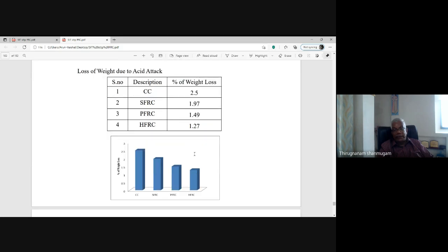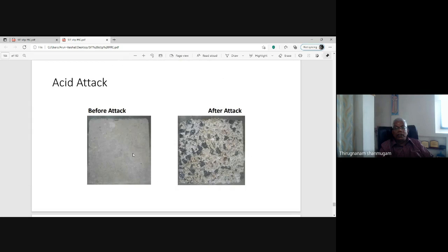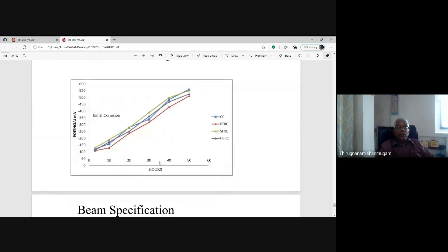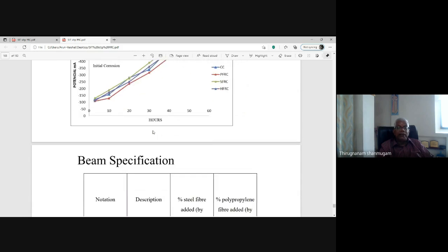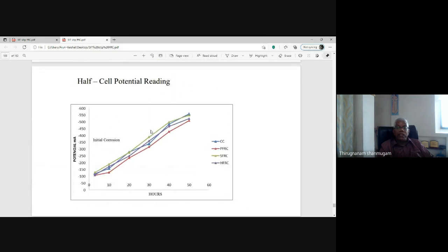Loss of weight is a durability criterion. Loss of weight in acid attack, sulfuric attack, is very much less, nearly 50% less. So hybrid fiber reinforced concrete is much more resistant to the acid attack. There is a view of the acid attack before and after the immersion. Half cell potential reading, corrosion attack is there. Here also you can notice minus 350 is the demarcation point, and it is having some particular limit.